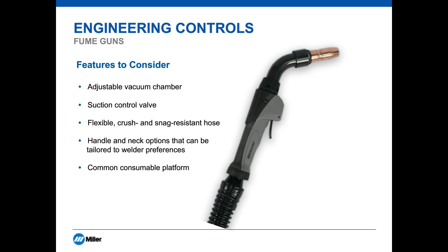Some other items about the fume gun: they normally are between 300 and 600 amps, and the higher the amp gun, typically it means that there's a little bit more weight to them. But that's not why you should pick the gun. The gun should be designed around the correct amperage and duty cycle rating when purchasing. Some other features to think about when purchasing fume guns would be an adjustable vacuum chamber. The chamber allows for better joint access and visibility of the puddle.